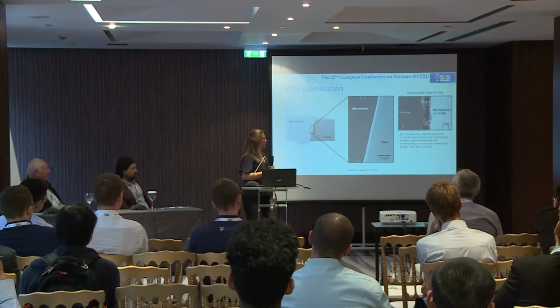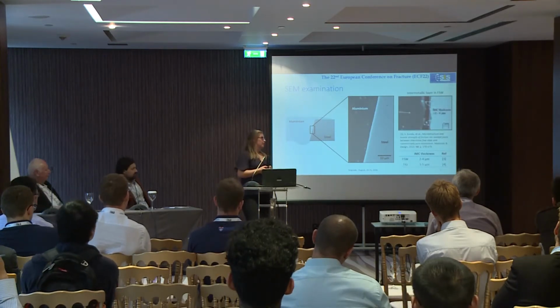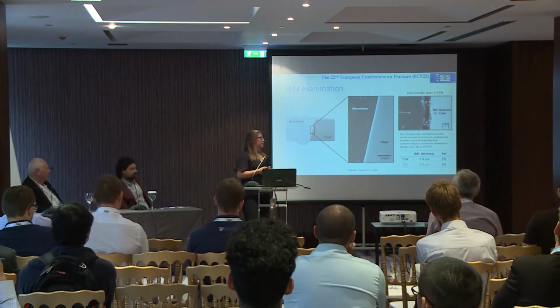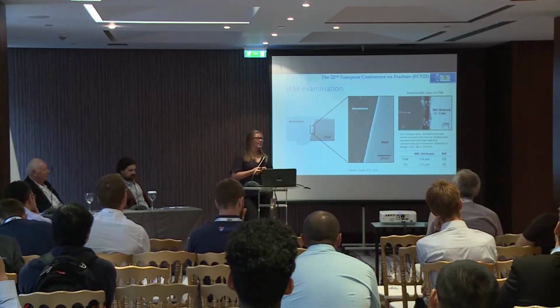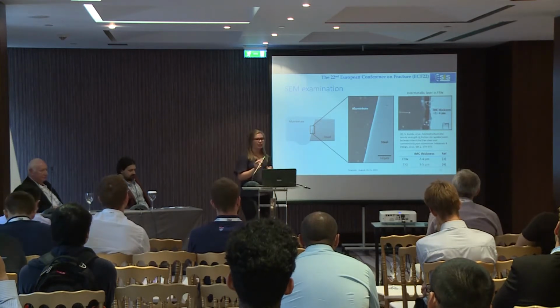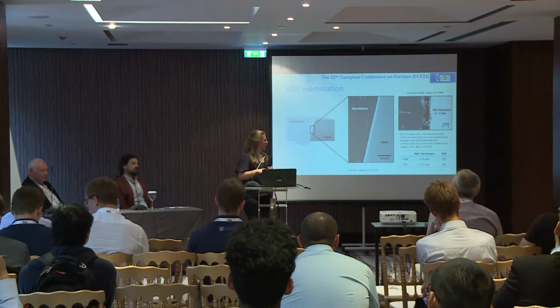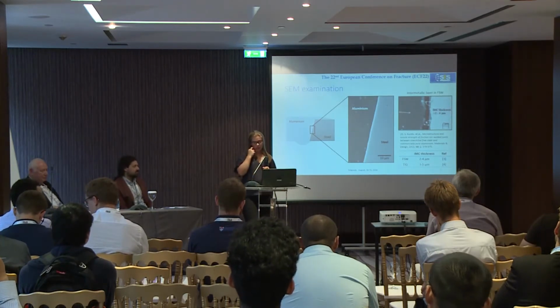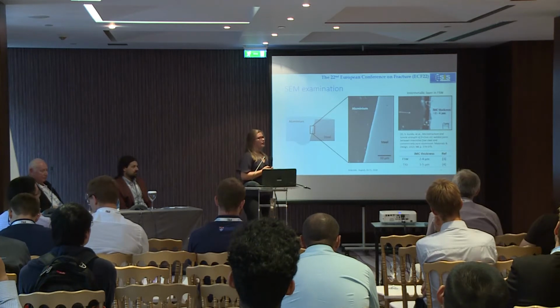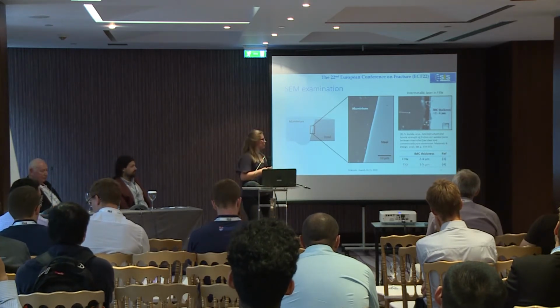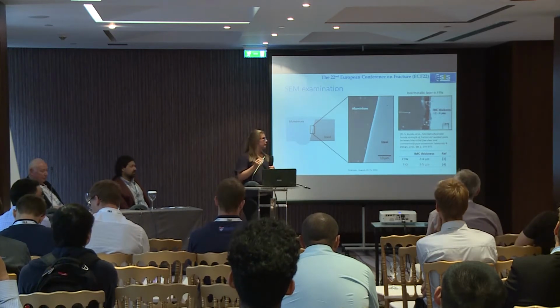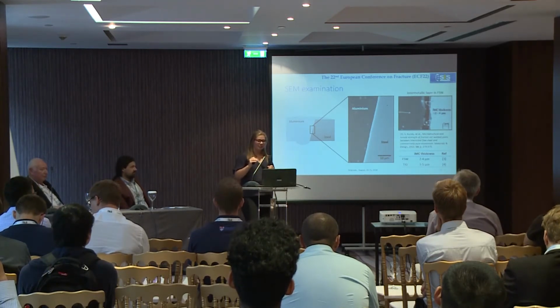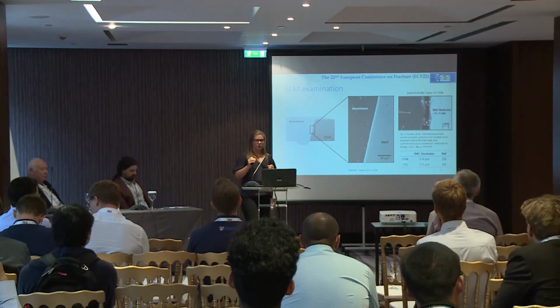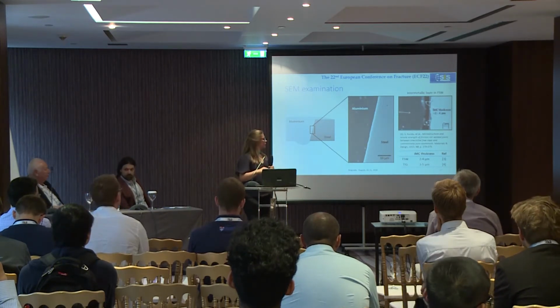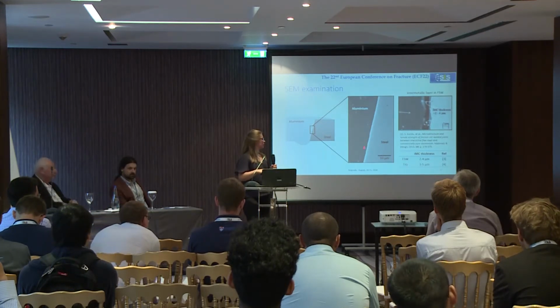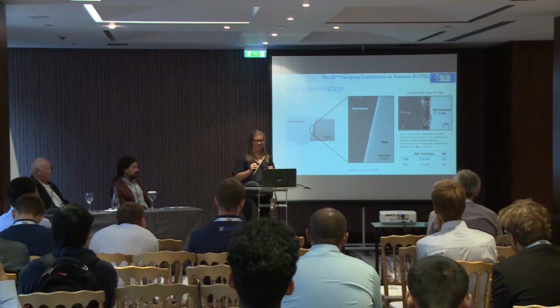This is also quite interesting, as in conventional welding techniques, such as friction stir welding and TIG welding, this intermetallic layer is possible to see. It's between 2 and 5 microns, and that means that in a standard SEM analysis it should be possible to detect this layer, because the lower limit that we can possibly detect is 0.1 micron, which means that, yeah, if there is anything in this bond line, it's lower than that.